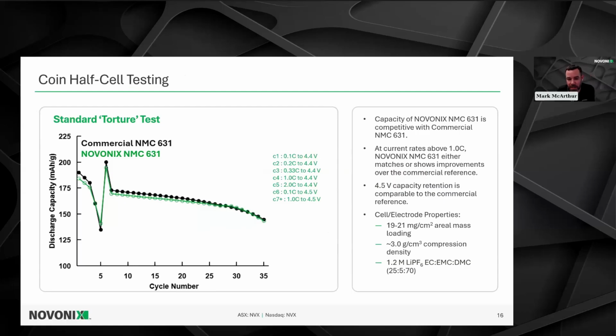So we can take these materials and do a head-to-head comparison in a standard, what we call torture test for these coin half-cell measurements that were done. And in here, we are comparing and contrasting the NOVONIX-made NMC 631 to a high-quality commercial NMC 631. And the cycling protocol is shown to the right of my figure, about in the middle of the screen, of what we're doing for each cycle. The electrode information is displayed in the text box to the right-hand side. What I really want to emphasize on this slide is when you compare the green open circles to the black closed circles, you see that our material is quite competitive to what could be purchased on the market today. This is one of the best NMC 631s that we have seen, and as such, this is why we use it as a benchmark for our own materials.